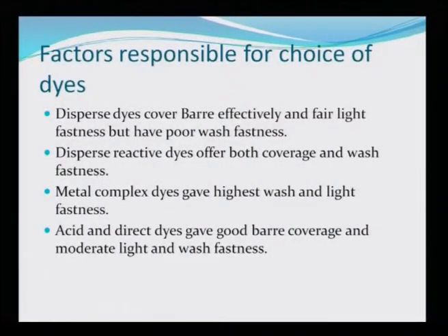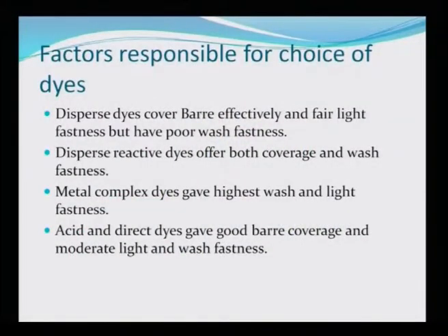Dispersed dyes cover barre effectively and have fair light fastness, but poor wash fastness. Dispersed reactive dyes offer both coverage and wash fastness. Coverage is also termed barre, that means how much portion of the surface of the fiber has been affected by the presence of the dye. So, if we look at simple dispersed dyes, they have good light fastness but poor wash fastness, and somewhat medium coverage, whereas dispersed reactive dyes have both good coverage and good wash fastness.